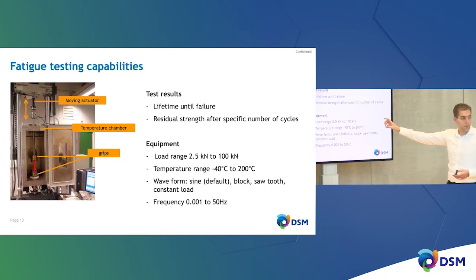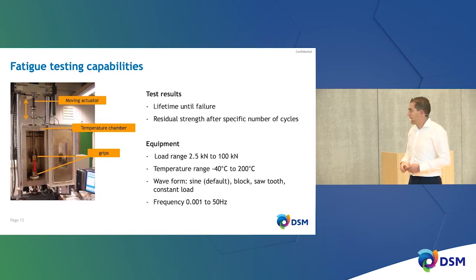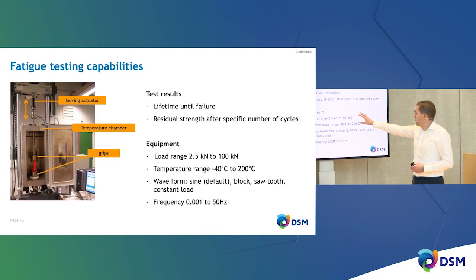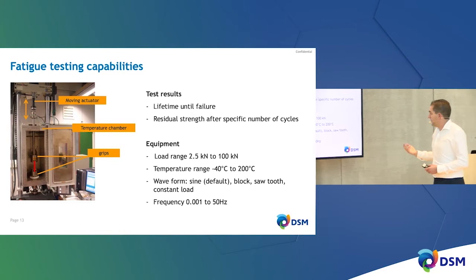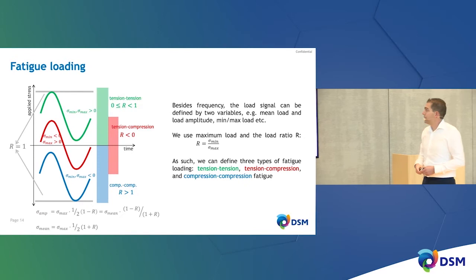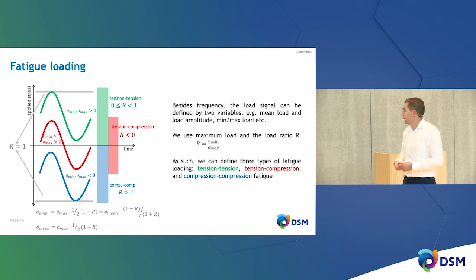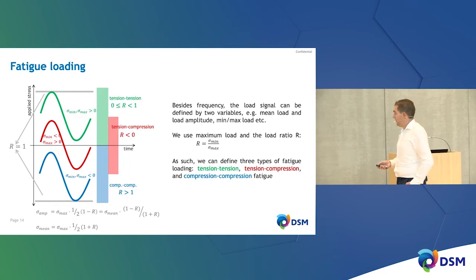You load the specimen and measure the lifetime until failure. The loading range spans 2.5 to 100 kN depending on the material, with temperature control from very low to very high. You can apply various waveforms and frequencies. The waveform can be defined by mean stress or load amplitude, and we use the maximum load and the so-called load ratio R, defined as minimum stress divided by maximum stress. If R equals 1, minimum equals maximum stress — that's just a creep or static load.